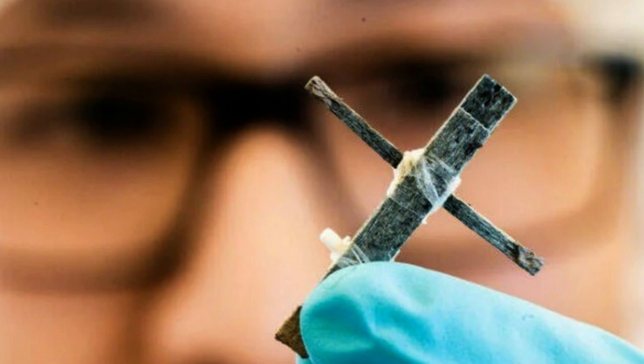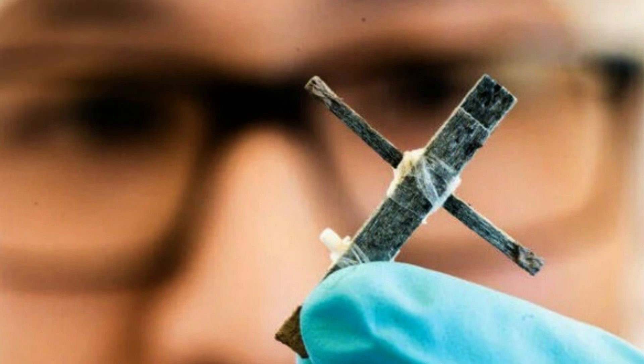This left behind a porous cellulose block ready to be drenched in conductive polymer. With the lignin removed, the researchers found that a water-soluble conductive polymer known as poly-3,4-ethylenedioxythiophene polystyrene sulfonate, or PEDOT:PSS, was the best choice for the job, since it behaved similarly to water and easily filled pockets in the balsa all the way down to its core.